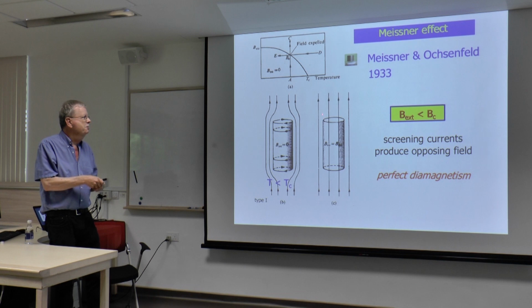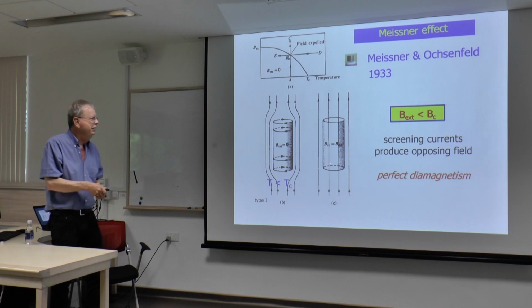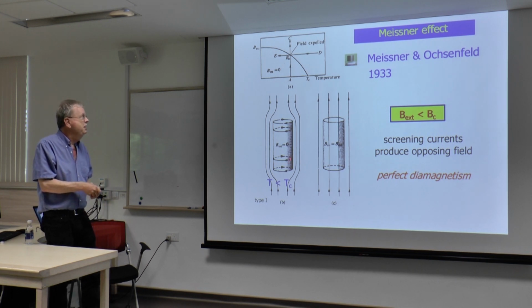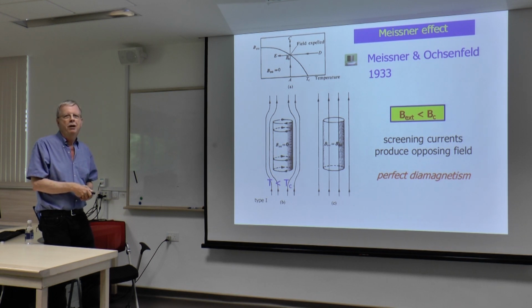If you cool through that, in ideal, rare cases, above TC you have a bunch of field lines penetrating your cylindrical sample. This is so you can get the demagnetization coefficient nicely. And if you go below TC, in ideal, perfect conditions, what all theorists believe, the flux is expelled. This almost never happens.